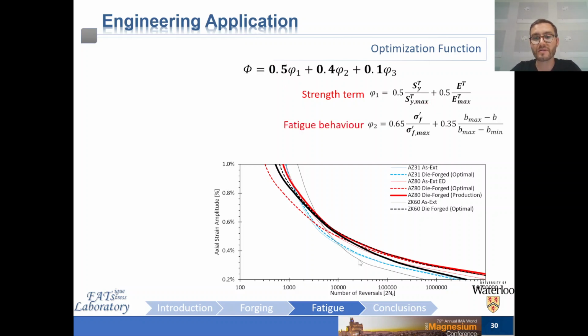The second term incorporates the fatigue behavior of the particular material in terms of the parameters extracted from a typical SN curve that many of you would be familiar with. And then finally, since fatigue is a defect-driven phenomenon, which is governed by the limiting location within the full-scale component that has the most inferior properties, the spatial variation is something that's very important. We looked at the spatial variation of the hardness, or the superficial hardness. That was considered to ensure we select a processing condition that produces uniform properties that are free of major significant defects. So that's the third parameter here, phi 3.